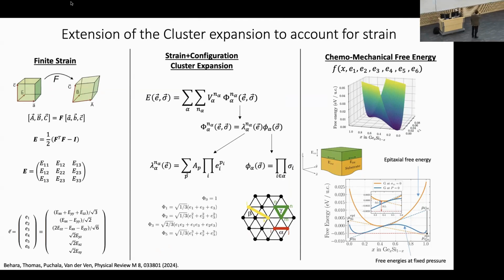I apologize for it, but this is just how to do strain rigorously. This is just the cluster expansion formalism when we allow for strain and chemical degrees of freedom. But the key takeaway are plots like this. This is a free energy curve of silicon germanium as a function of composition and as a function of strain. So you can formulate free energies that are functions of not only composition and temperature, but also explicitly as a function of strain. And that way you can then analyze, okay, if you strain it, how does that change the free energy, and so forth. And it allows you to go beyond nonlinear elasticity because the curvature is related to the elastic moduli, and this curvature is clearly not constant as you change composition or as you change strain state. So anyway, a new thing that we've recently developed.